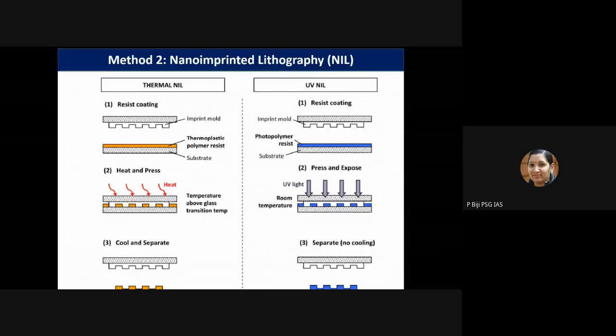In the thermal NIL, there will be a resist coating and an imprinting mold, which we have to fabricate ourselves according to our design. And then there will be a thermoplastic or polymer resist. You can either use a polymer or a photoresist on the surface of the silicon wafer substrate. Then you bring this imprint mold down towards your polymer resist film, and heat is applied, because the polymer has to be a little bit soft to have a proper molding or stamping process.